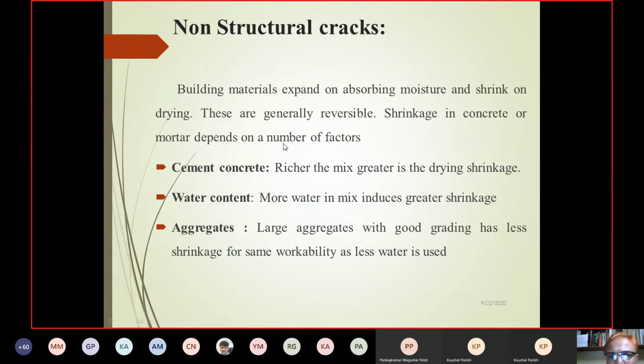One thing we have to take care about non-structural cracks. By small points we can avoid them. The building material expands on absorbing moisture and shrinks on drying. These are generally reversible. Shrinkage in concrete or mortar depends on a number of factors. One, cement content: the richer the mix, the greater the drying shrinkage. It is obvious. When the mix is richer, we have to go for good curing. Then water content: more water in the mix induces greater shrinkage, obviously. Then large aggregate with good grading has less shrinkage for the same workability, as less water is used. These are very basic points, but somehow they are not executed as we think.